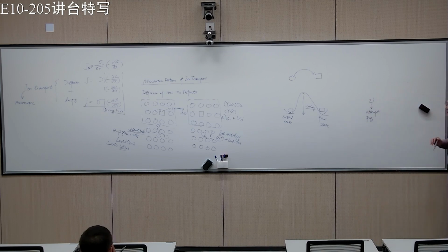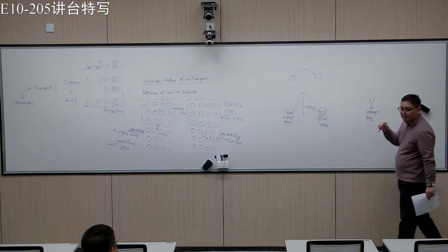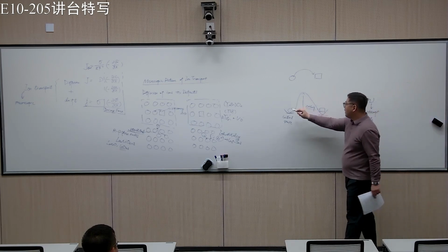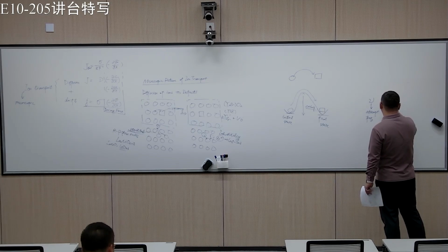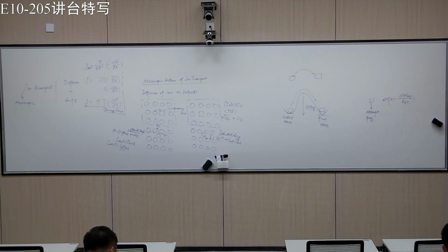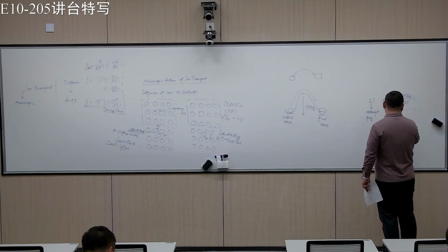That means per second, how many times the ion is trying to jump over to the other side. Of course, only very few jumps can succeed, can overcome the barrier to the other side. So we have some kind of exponential function to evaluate what percentage of the jumps will be successful. Okay. So this is basically the success rate.